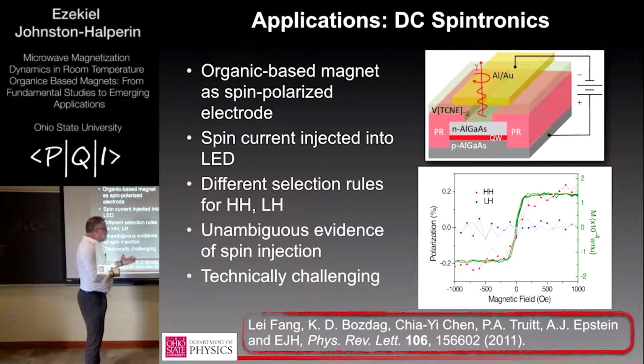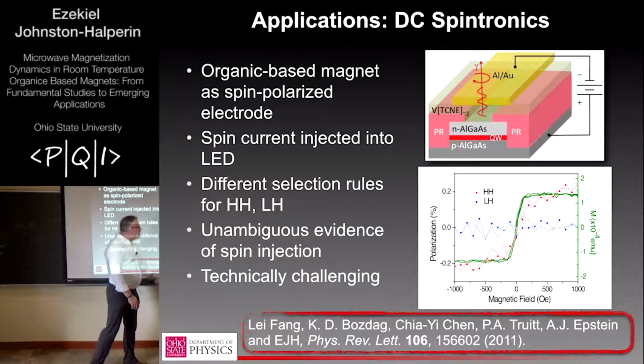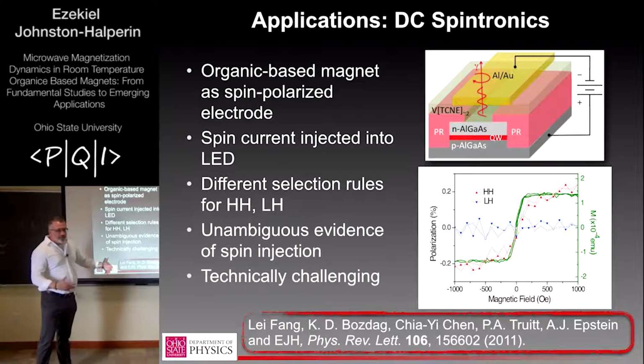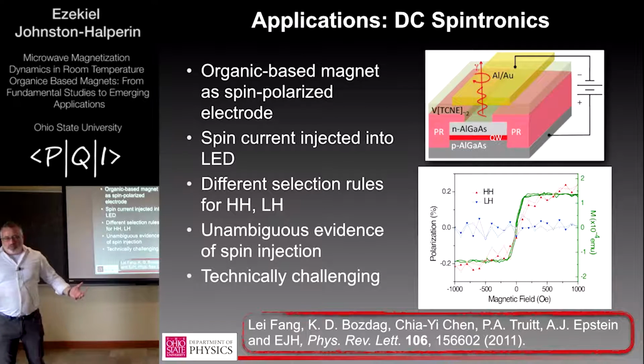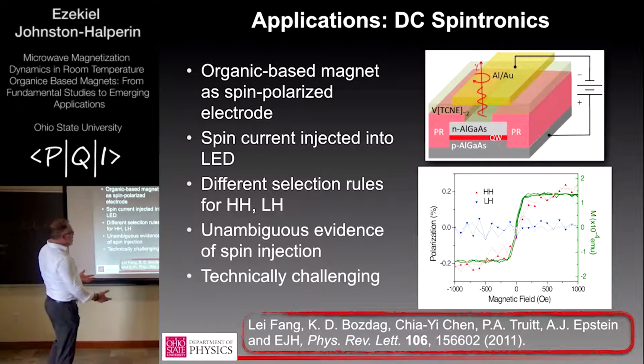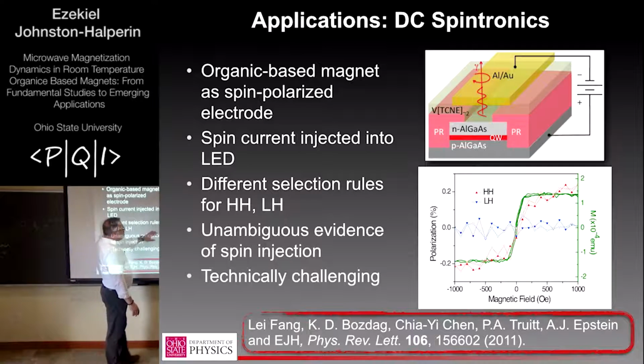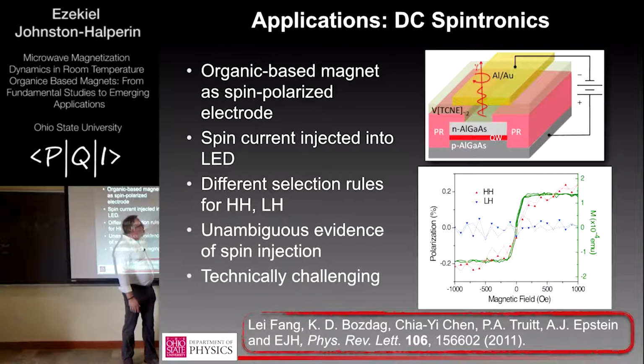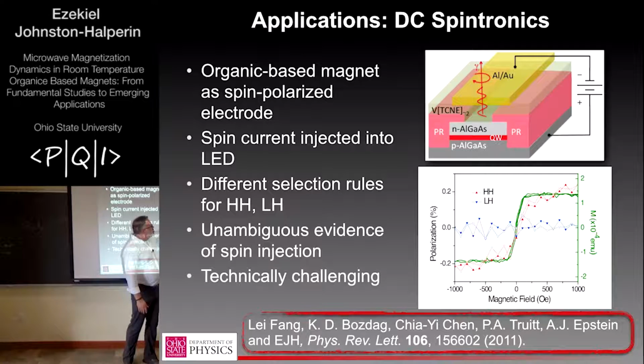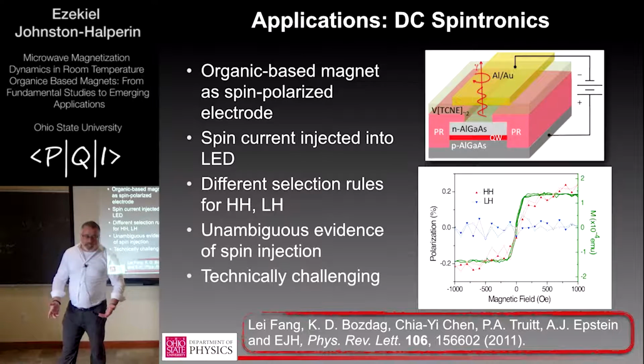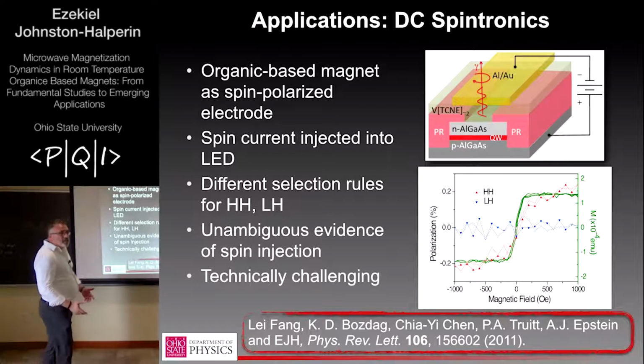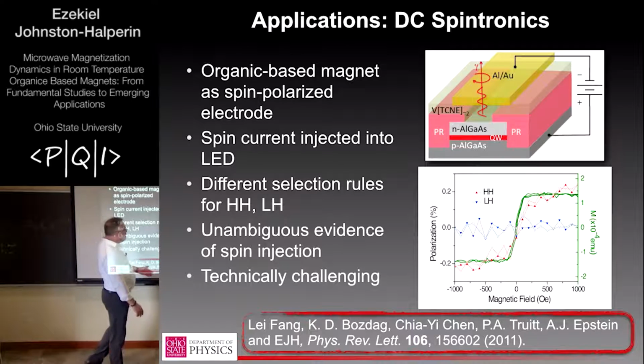This was the first experiment we got involved in, in 2011, which was appropriate at the time for interest in spintronics. It was all about generating spin polarized charge current. So we made an LED structure and deposited a thin layer of VTCNE on the N-type electrode. Driving current through the VTCNE layer acts as a spin filter. So you're injecting spin polarized carriers into this quantum well, and then by monitoring the polarization of the electroluminescence, you can monitor the spin polarization of the electron current.